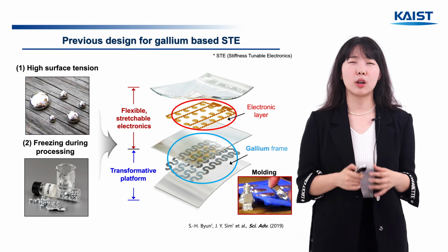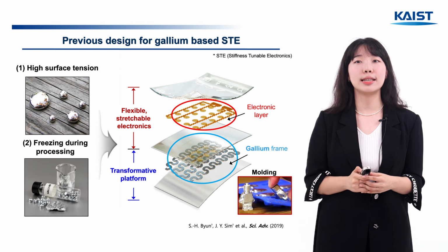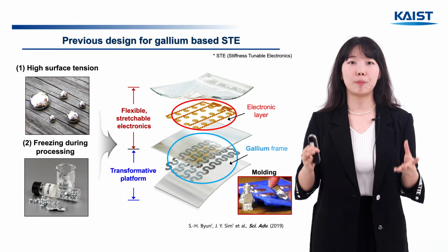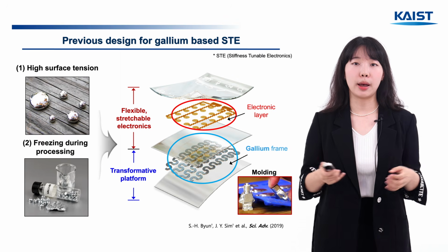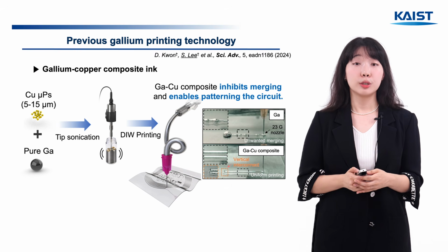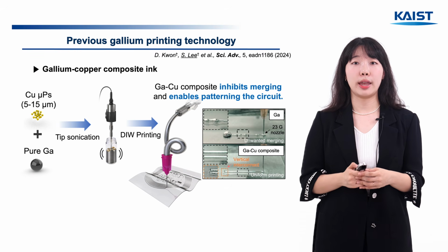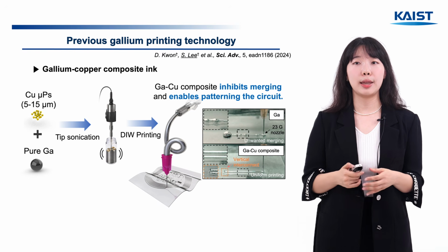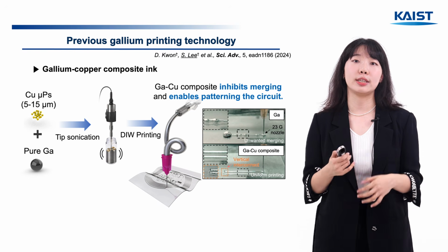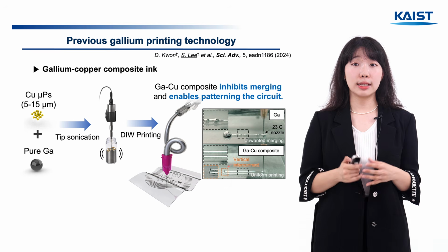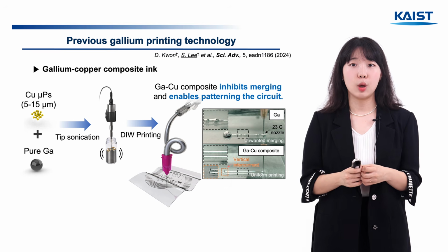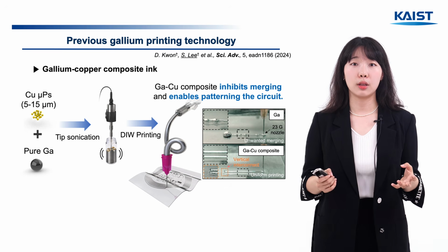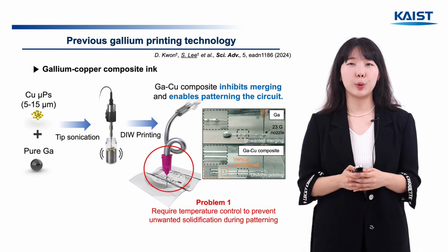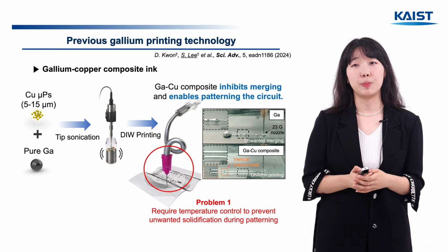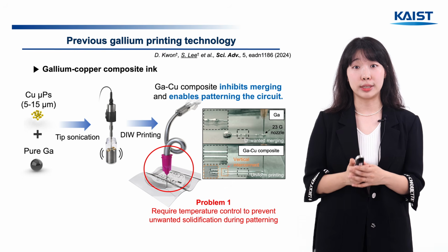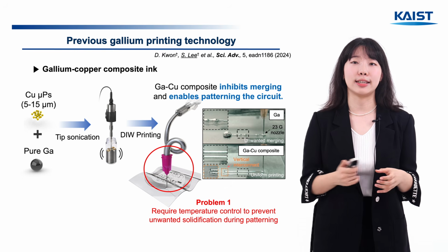But bulk gallium is hard to process, so until now, it has only been used as a thick mechanical frame fabricated by a mold. So to address this, I developed a gallium copper composite ink made by adding copper to gallium using tip sonication. This solved the ink's merging problem, which made circuit patterning possible. However, its freezing point was still similar to bulk gallium, so it kept freezing during the process, so I have to heat it constantly.